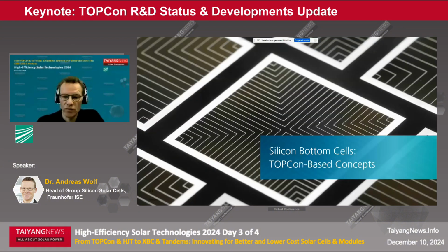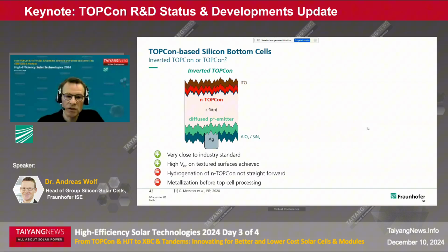Finally, looking in the future, we also think that TOPCon-based cells are a very good choice for bottom cells in multi-junction or tandem devices. In principle, there are different options to use TOPCon cells as bottom cells. This is a straightforward approach that we call inverted TOPCon, where you just flip the current TOPCon structure and you have the N-type TOPCon layer on top, and you replace the silicon nitride layer by an ITO layer, and then you can process the top cell on this. It's very close to industry standard, but there are some challenges that we see, which is the hydrogenation of this interface, which is not straightforward if you don't have the nitride layer in place, and also finalizing the metallization before the top cell processing poses some challenges in our view.